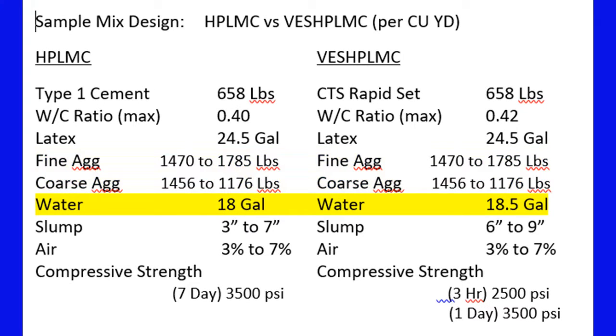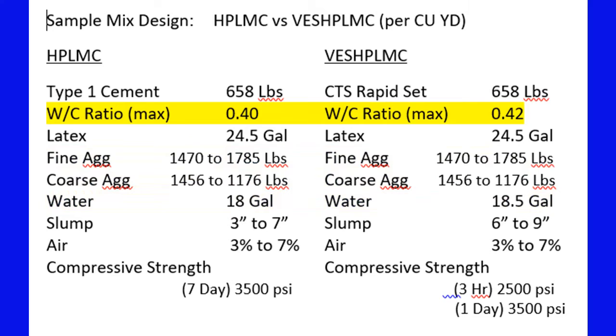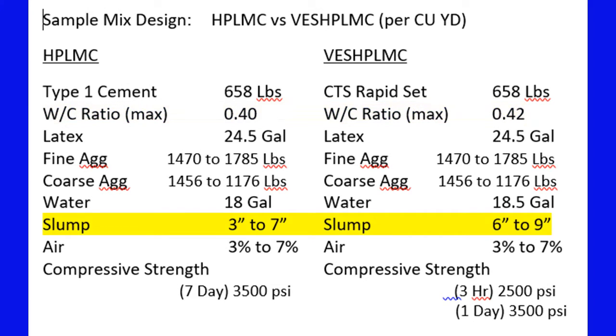VESHPLMC does require a little more water, though, for the hydration process. Typically, the water-cement ratio for VESHPLMC will be specified at a maximum of 0.42. The slump for testing purposes is generally allowable at between 6 inches and 9 inches. The mix will discharge in a very fluid condition, but quickly firms up.